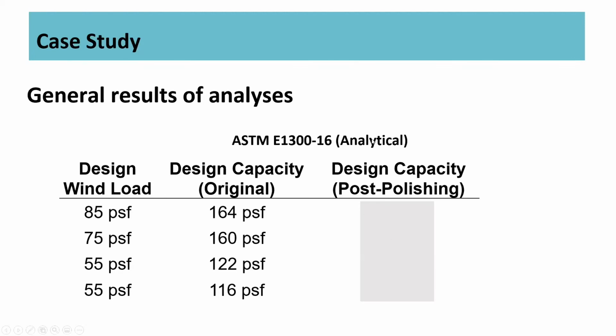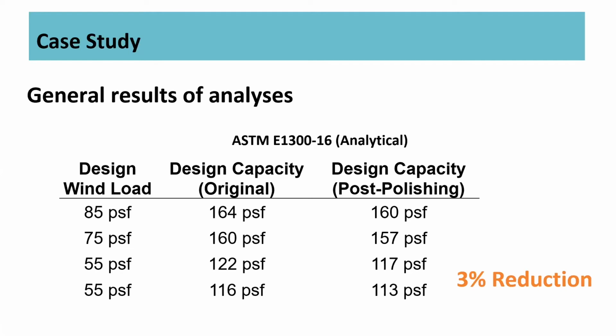And so what we did is we went ahead and applied the post measurement data. And we see that, in fact, those did reduce, but they did not reduce much. In fact, it was about a 3% reduction in that capacity. And those are still well beyond, almost double in each case, the original design load. So we resolved in this case that there was plenty of capacity post polishing for this test case. So that's great.